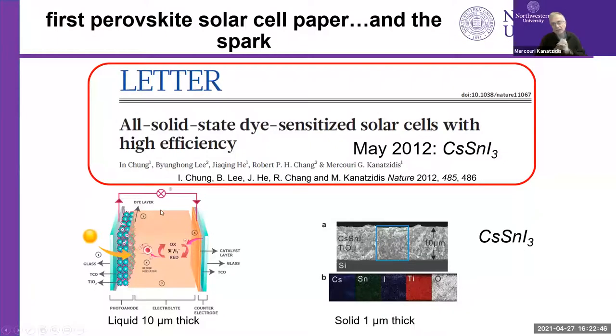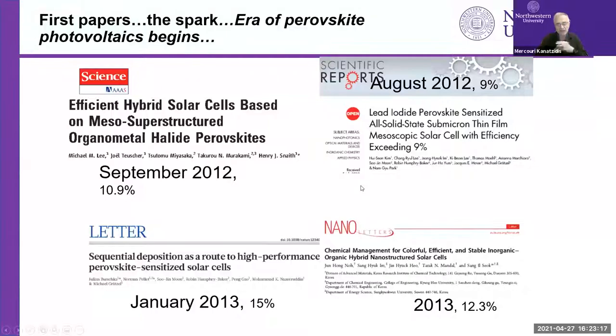Now, back in 2012, we published a paper in Nature using this perovskite material, cesium tin iodide, as a semiconductor for a solar cell material. And we published 10% efficiency. This was the first paper reporting on a solid state solar cell using a perovskite material, and it surprised everyone. That was in May of 2012. And then 3 or 4 months later, a number of other groups published similar papers with similar efficiencies or higher, using also perovskites as well.